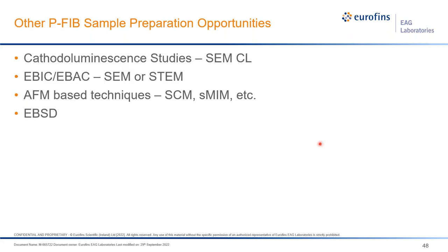So some other opportunities that I don't have data for at the moment to share with you are also for things like cathodoluminescence studies, so SEM-CL or even STEM-CL. Also looking at things like electron beam induced current or electron beam absorbed current studies, so EBIC or EBAC, both in SEM or STEM. In this case, using non-gallium allows us to retain the electrical properties in the sample much better, with much better signal and noise for the analysis, because we don't have an ohmic surface layer that can bleed off charge. So we can collect all the current that we're creating from the technique versus losing it to the damage layer on the outside of the sample.